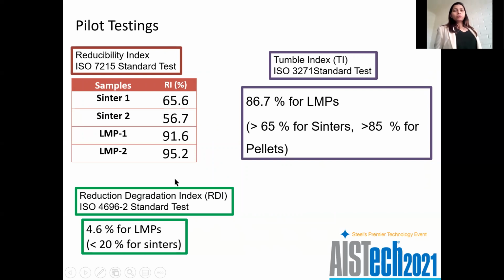All the pilot testings were based on the ISO standard tests. The reducibility index was measured by the standard: reduce 500 grams of samples at 900 degrees for 3 hours, with 30% CO, 70% nitrogen, at a 15 liter per minute flow rate, and whatever the degree of reduction is after 3 hours is considered the reducibility. The reducibility of LMPs was found to be more than 90 percent. The acceptable reducibility of sinter is more than 60, for pellets more than 70, and the reducibility of LMPs is quite high.